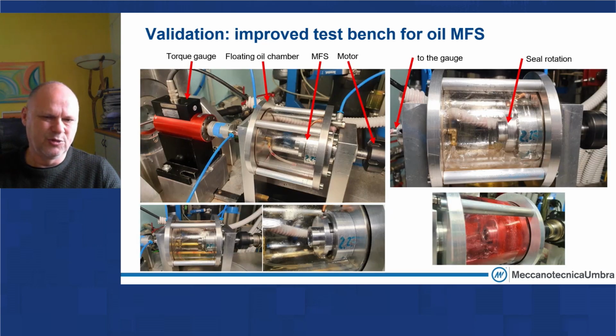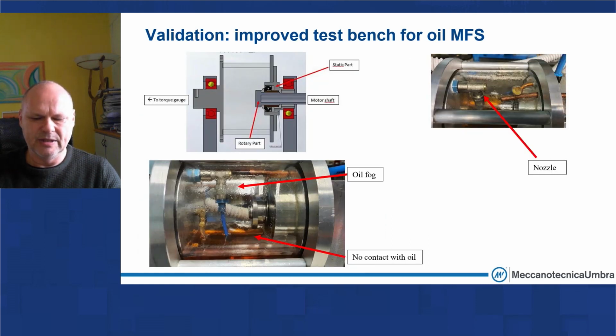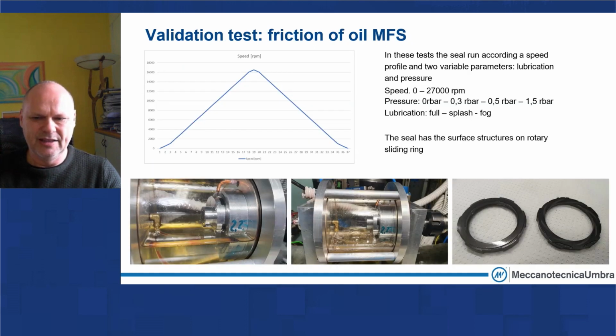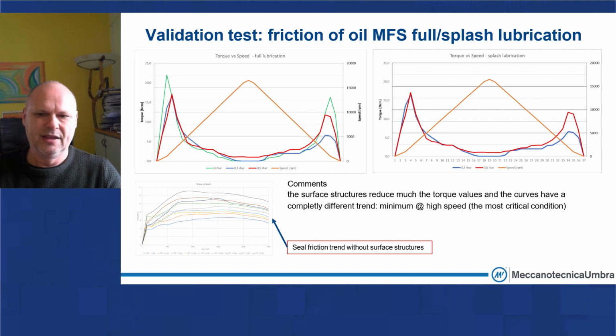We are able to measure the torque using a floating chamber. So in this case, we perform the measure in static condition instead of dynamic condition. We simulate in this test bench 3 different lubrication conditions: full lubrication, splash lubrication, and fog lubrication. This is an important difference because what we obtained in the 3 different lubrication situations is different.